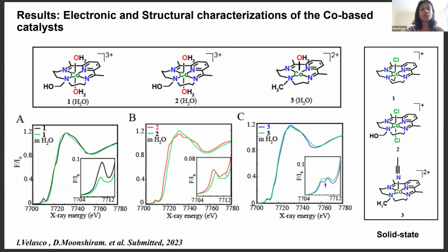Interestingly, the pre-edge feature also changes as the complex becomes more centrosymmetric. So because of this, you have less mixing between the 3d and the 4p states. By contrast, for catalyst 3, we observed that the XANES and the pre-edge are around the same. If, for example, it were to lose the water molecule completely, we would have seen a more intense pre-edge feature as well as a more intense 1s→4pz transition. But if it were octahedral, the 1s→4pz transition would be indistinguishable from the white line.